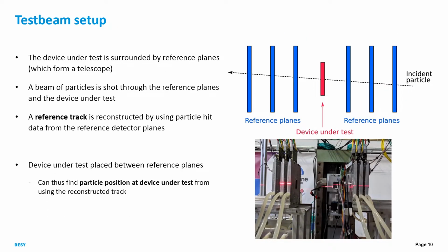Now, a test beam, just briefly how a test beam works. So we have a device under test, which is placed between reference planes, and these reference planes make up a telescope. And then when we shoot particles through all this, we can use the reference planes to reconstruct the particle track. And from this, we can extrapolate, so we can find the position the particle was at when it hit the device under test. And then we can see how the device under test responds to a hit in that position.